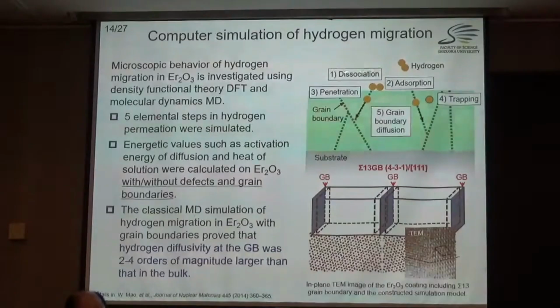And we also constructed this idea on grain boundary structure, grain structure. This is also experimentally confirmed by TEM observation. So this is a grain boundary. As a result, the diffusivity of hydrogen in the grain boundary is 2 or 4 orders of magnitude faster than in the bulk. So the grain boundary diffusion is much faster than the diffusivity in the bulk. This agrees with the experiment.